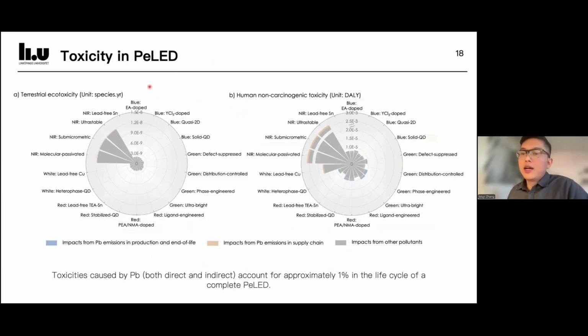Toxicity is always the largest controversy or concern for the perovskite devices, but normally our concern about lead is just an intuitive conclusion and lacks real data support. So here we want to evaluate the toxicity of PeLED across the entire life cycle to check the effect of lead. In short, I just skip the process, but in short, we find that the lead-related toxicity only contributes about less than 1% of the total environmental impact in the full life cycle. That's very far lower than what many people might expect.